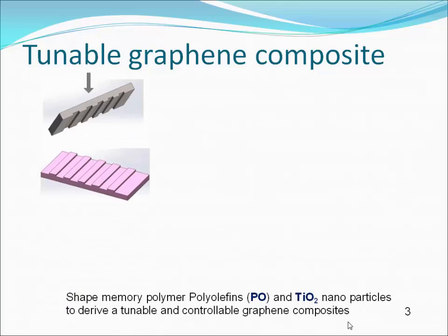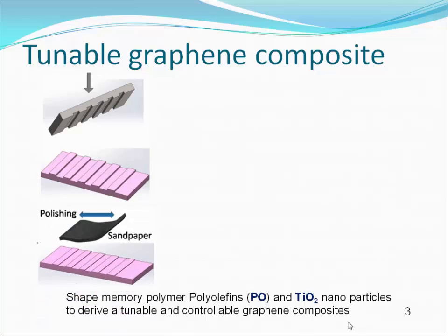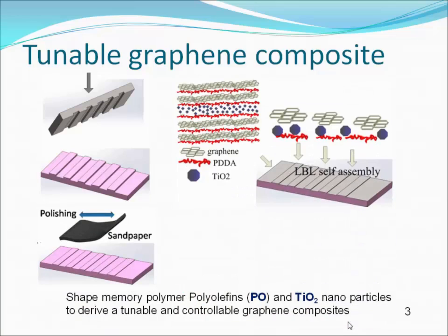First, a silicon mold is placed on PO polymer, and we use hot embossing to transfer the patterns from the silicon onto the PO. And we used sandpaper polishing to remove those patterns. Next, we deposit layer-by-layer graphene on the surface of PO polymer, instead of a regular layer-by-layer graphene that I've just mentioned previously. We add titanium oxide nanoparticles in the center of this sandwich structure because it can change and tune the properties of these graphene components.